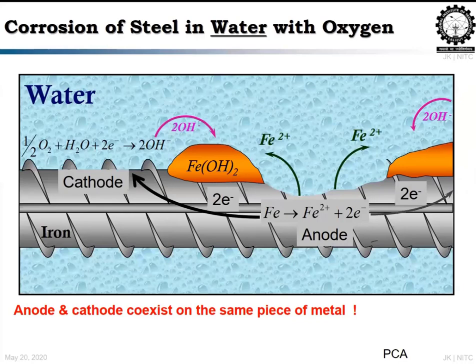We can see the rust on the steel, where it forms an anode and a cathode in the same steel bar, and it takes the moisture and water and forms ferric oxide, hydroxide. So this is a very common reaction, and it creates a very uniform corrosion. The corrosion will happen throughout the steel structure, it means throughout the steel bar. So the loss of metal along the length of the structure will be comparatively less. I'm not saying that we don't need to bother, but it is comparatively less.